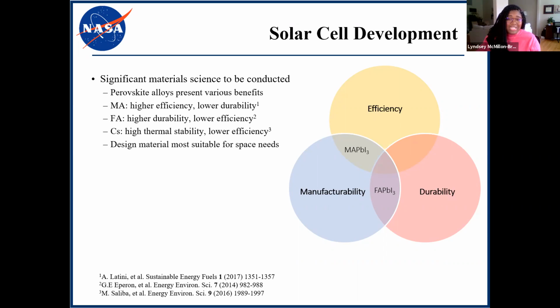Formamidinium lead iodide has a higher durability, but tends to have a lower efficiency. And unfortunately, this pure FAPI lacks structural stability at room temperature because it can crystallize into the photo-inactive non-perovskite delta phase, which is also commonly known as the yellow phase, while the ideal black phase is very sensitive to humidity.